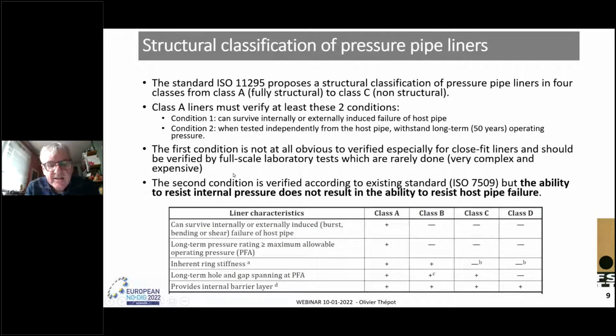The standard ISO 11295 proposes a structural classification of pressure pipe liners in 4 classes, from class A, fully structural, to class D, non-structural. A class A liner must verify at least 2 conditions. First condition, it can survive internally or externally induced failure of the host pipe. Second condition, when tested independently from the host pipe, it can withstand long-term, 50 years, operating pressure.